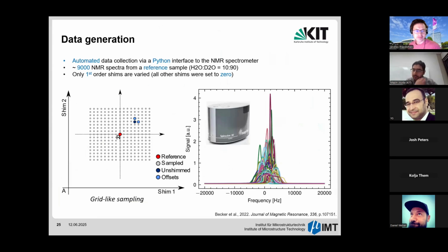Yeah, that's a very good question. So what we did here is we used this magnet here to collect the data. We started from a trimmed situation where we have a good spectrum, and then we purposefully distorted that spectrum by applying a distortion along X, Y and Z. And then we recorded the corresponding spectrum. And the idea here is that we then feed this distorted spectrum to the model as an input, and we tell it that whenever you get this distorted spectrum, you should predict those X, Y, Z values as the corresponding values that could correct this spectrum.